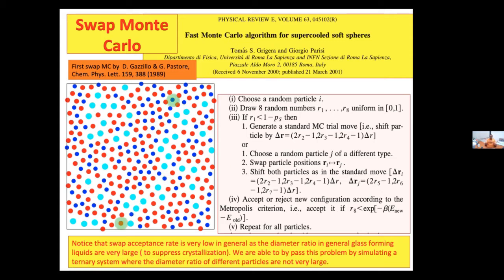So just this extra step of particle swapping actually dramatically improves the relaxation process in this system. In this paper, they were able to show that the relaxation process can be enhanced by many orders. The model that they looked at was a binary glass forming liquid, but because the particle size ratio wasn't very big, this glass forming liquid was very prone to crystallization. And if you look at this cartoon carefully, imagine that you have different types of particles, so let's say binary in one occasion, and then you have a large and a small particle.